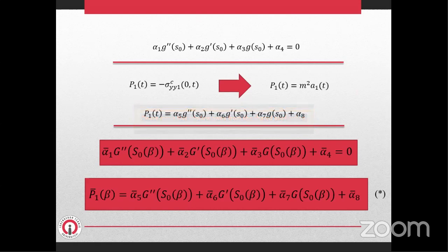We anticipate that in practice, at very short times in solidification, like right after the molten metal hits the mold surface, the problem is effectively uncoupled. Hence, the predictions of the present model provide some indication of possible groove instability, particularly in the early stage of the process. We determine the first order contact pressure at the shell coating interface by using this equation, and it is calculated as this last equation.